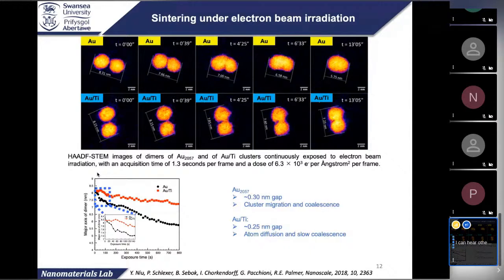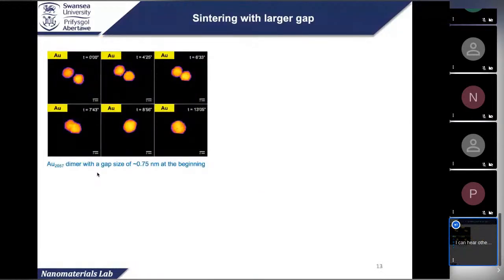So here we show that if you put titanium in the gold particle, you just slow down the sintering process. This is the case with a 0.3 or 0.25 nanometer gap in between. Then we studied the nanoparticle with a larger gap. So this is a gold particle with 0.75 nanometer in between. You can see after 13 minutes, they can still move around and become one particle.